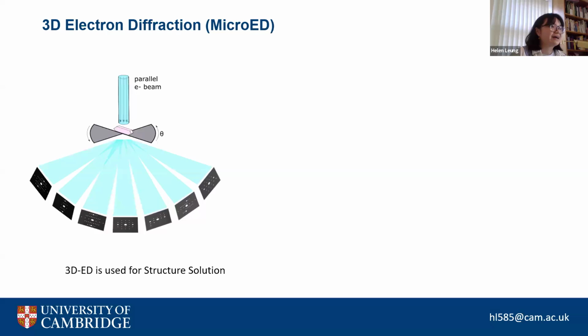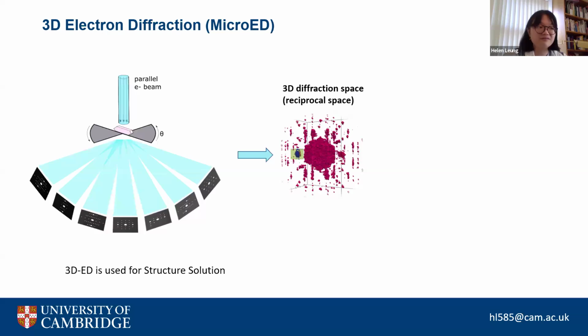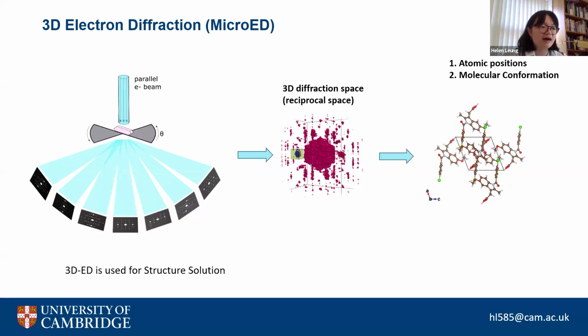Okay, so 3D electron diffraction, some of you might know it as micro-ED, it's also got many other names in the literature, is analogous to single crystal X-ray diffraction, and it's essentially where we take a parallel electron beam in our microscope, so we're in TEM mode, and we tilt a crystal around a range of rotation angles, and at each rotation angle we would collect one pattern, and this gives us essentially a tilt series. And when we reconstruct that in reciprocal space, we end up with a data set that's essentially analogous to a single crystal XRD, so classic crystallography, and we can therefore extract atomic positions but also molecular conformations.